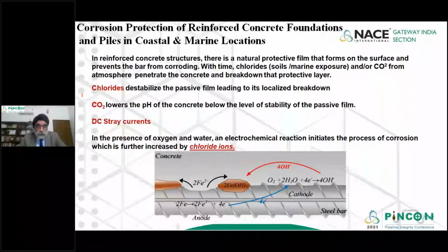Above ground, carbon dioxide in the air basically penetrates through the concrete cover. It lowers the pH around the steel rebar, which causes the loss of the passive film on the rebar, and again starts the process of corrosion.